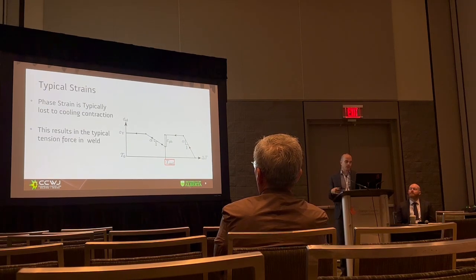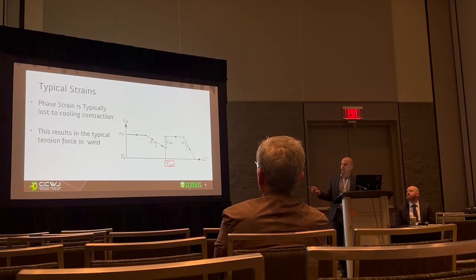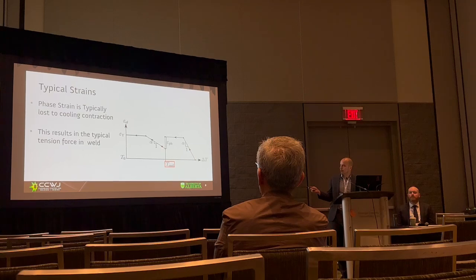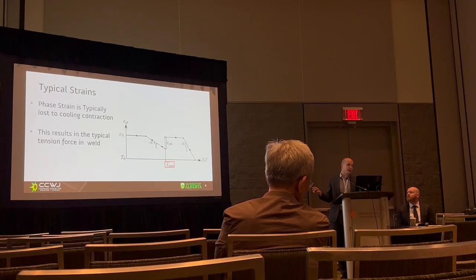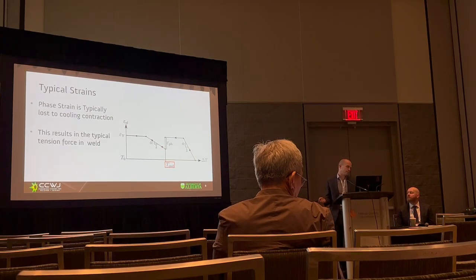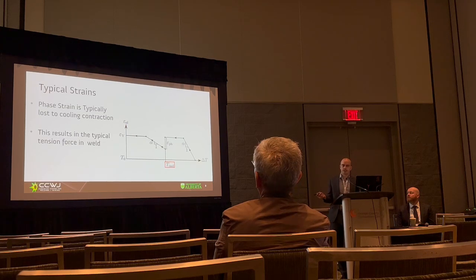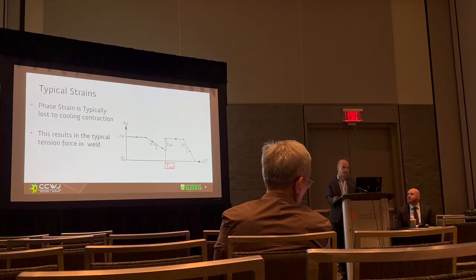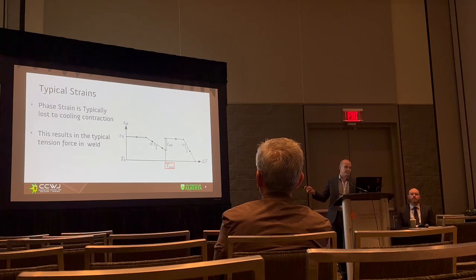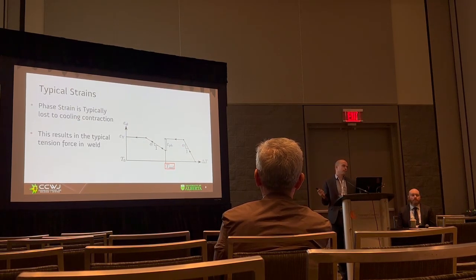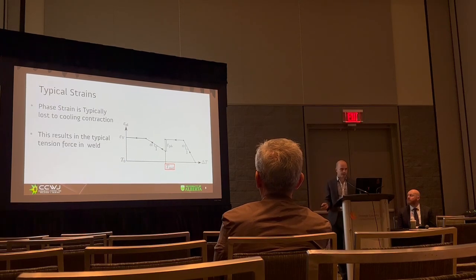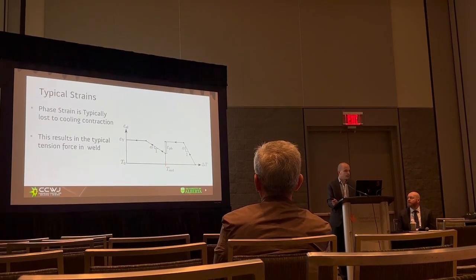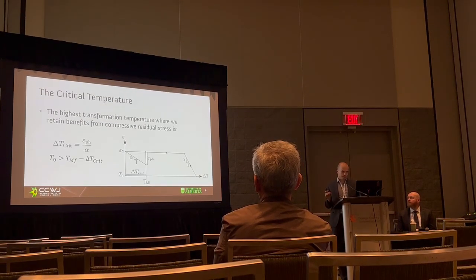And ultimately, what we've established happens most of the time in most welded materials is you transform to martensite, and then you keep cooling down, and you just yield again, and you're back in tension. Because the final residual stress state depends primarily on the strain experienced before reaching equilibrium temperature, it doesn't matter when this happened or how much it happened. If you hit this yield tension force again, you're back where you started, you're in tension, things want to crack, right? So what we said is, well, we can look at this.